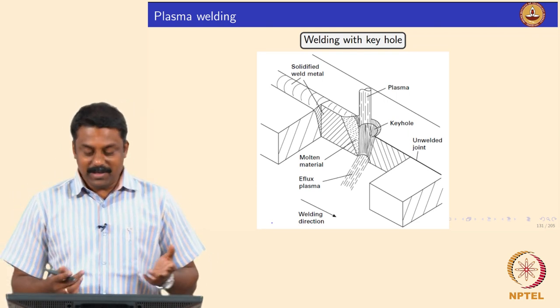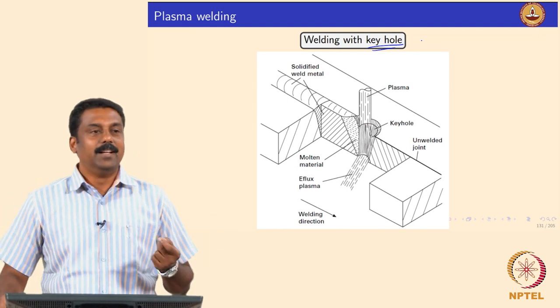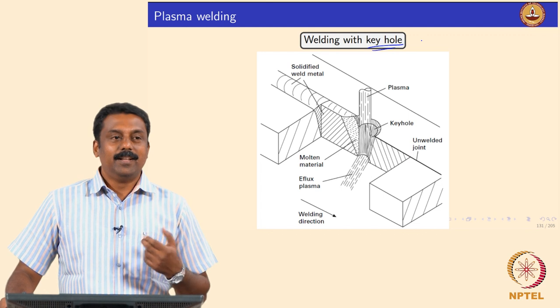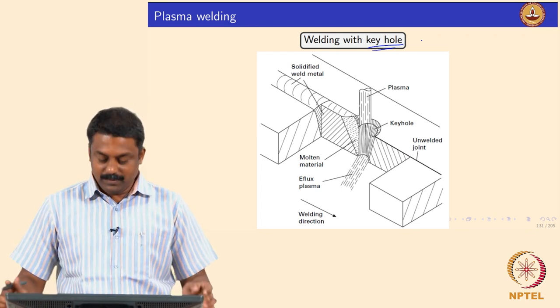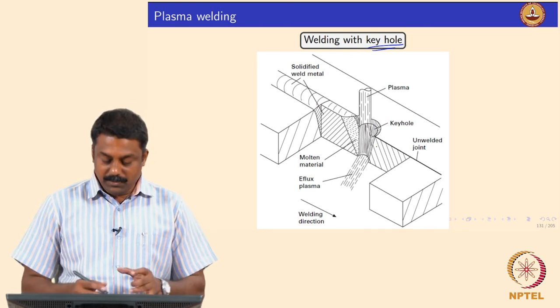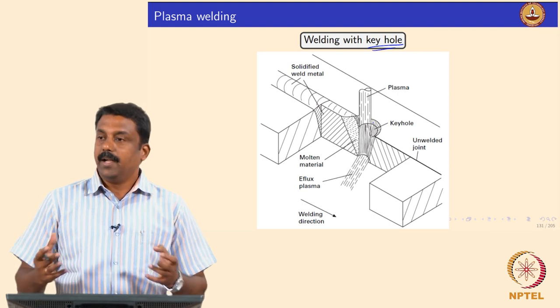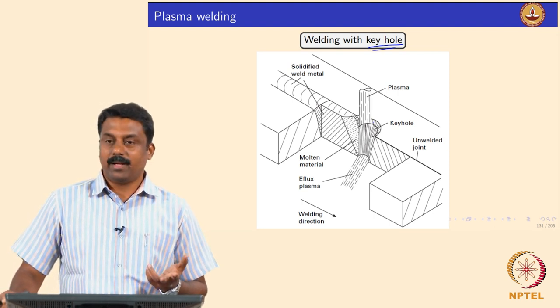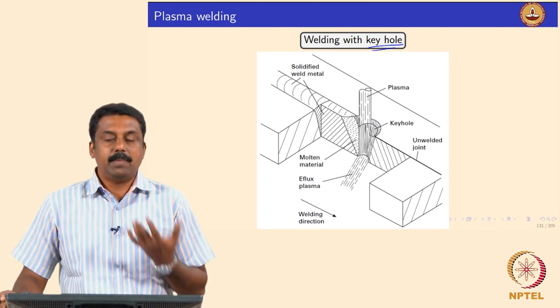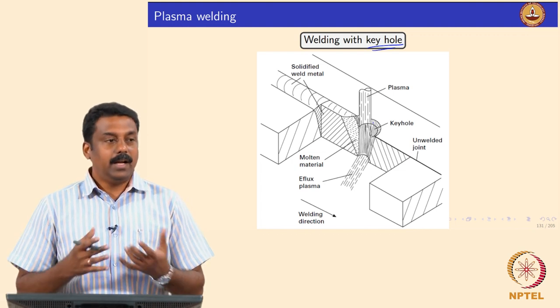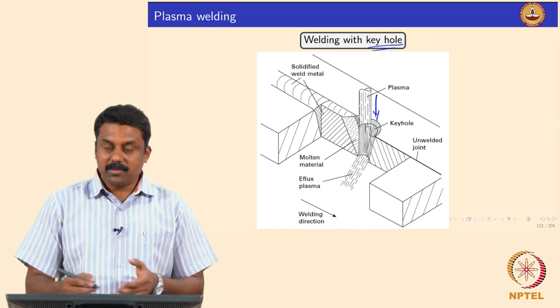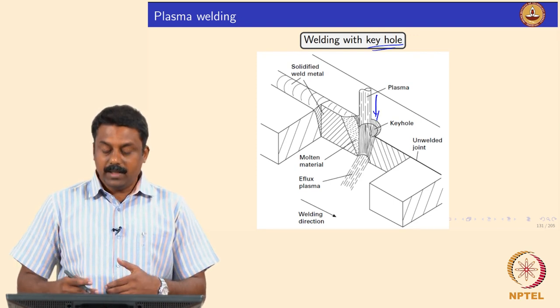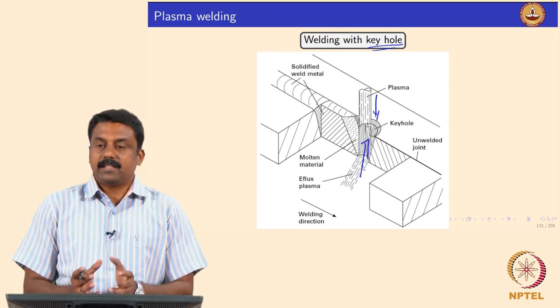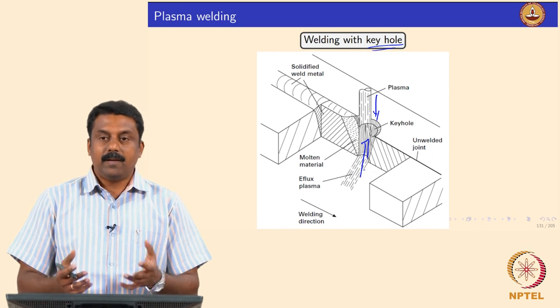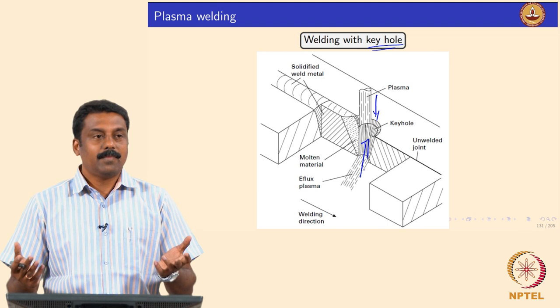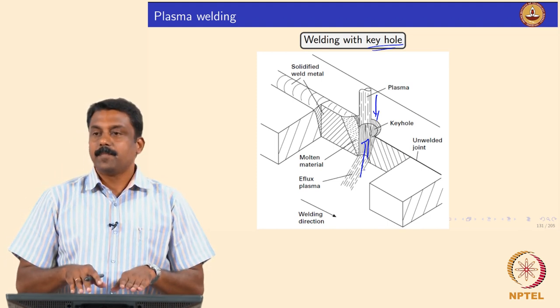So I mentioned keyhole, right? Keyhole is one characteristic you always see when you are doing power beam welding, for example laser. When you are using laser or plasma, you will have a complete penetration, and once the penetration is made, liquid is formed and you start vaporizing the liquid metal. Once the liquid metal forms, you also generate a vapor pressure. So you have the vapor pressure and the plasma jet velocity which you are sending towards the work pool. Then when the vapor starts escaping from the molten pool, you also have a recoil pressure. It is like a rocket. When vapors are going up, it is also pushing, isn't it?